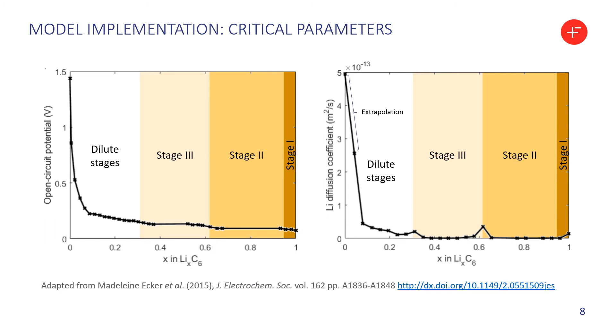The critical parameters for this lithium plating model are the open circuit potential and lithium ion diffusion coefficient in the graphite negative electrode on which the lithium is plated. Looking at the open circuit potential on the left, between the phase transitions it is completely flat — only at the phase transitions is there any variation. On the right is an unlogged version of the diffusivity graph shown earlier, and again you see that only at the phase transitions is the diffusion coefficient even visible; between the phase transitions it is virtually zero.